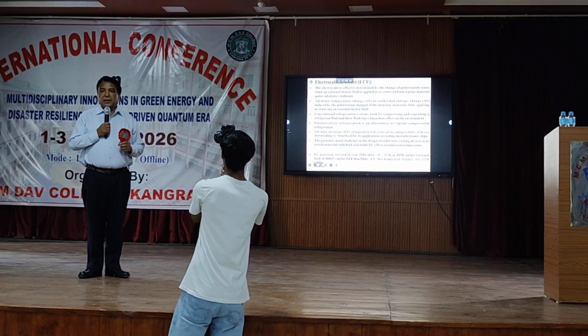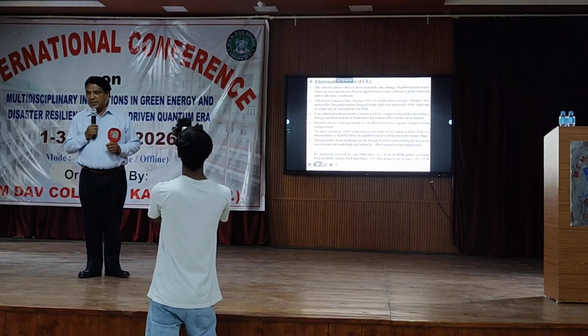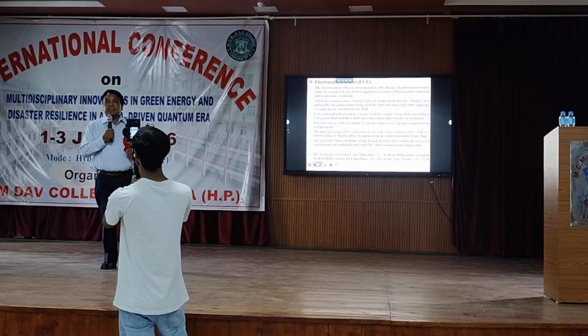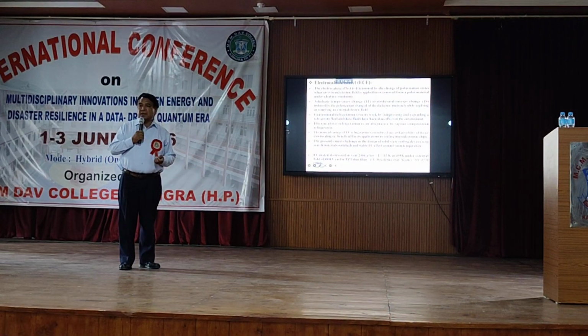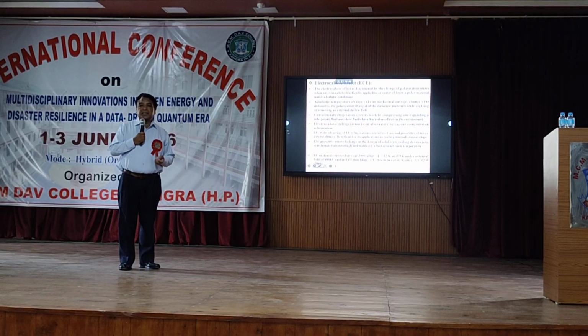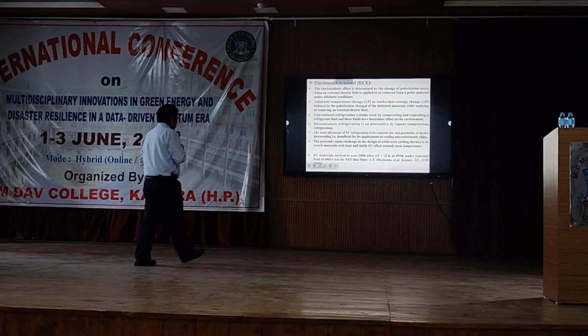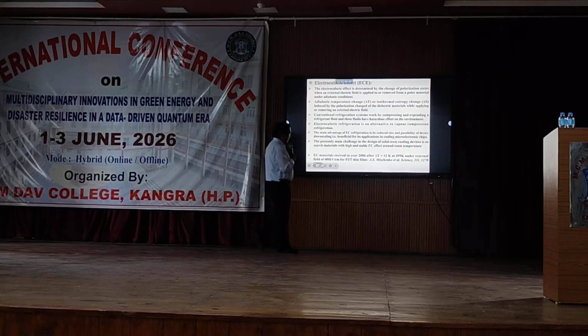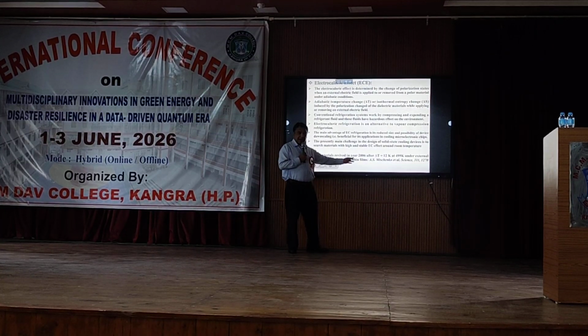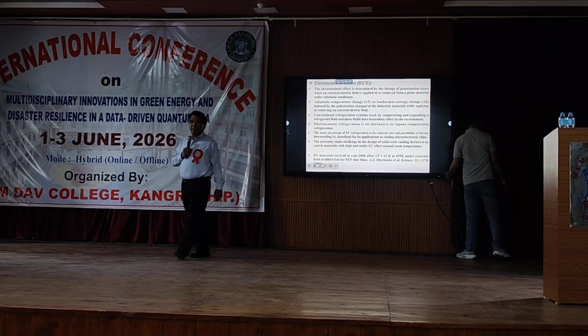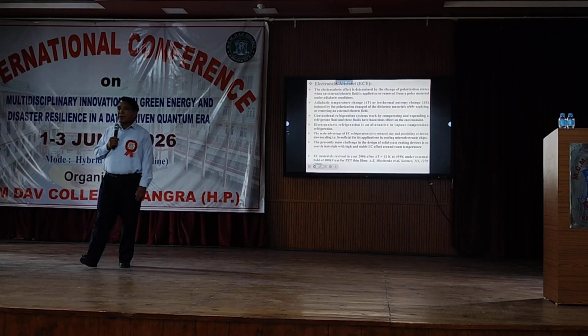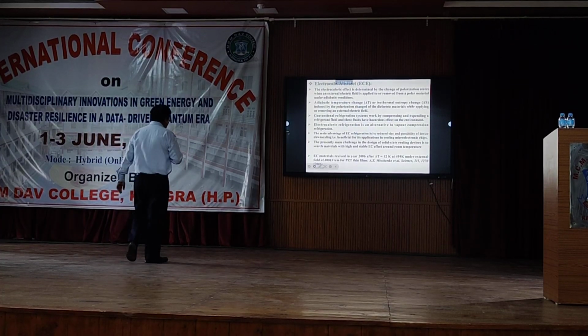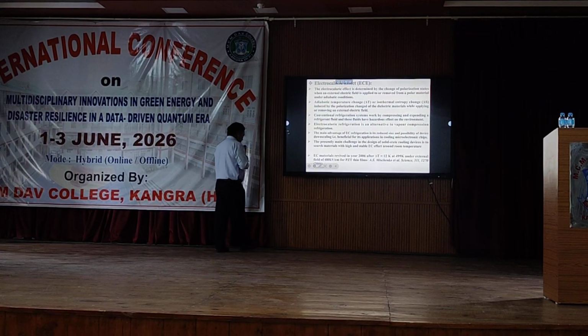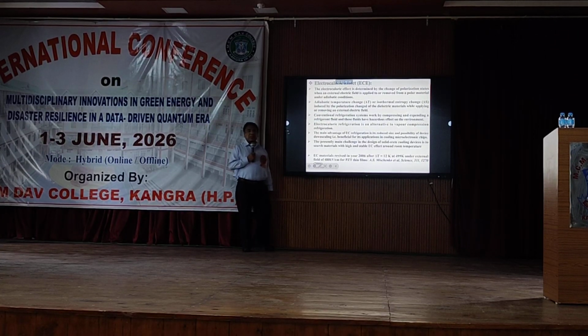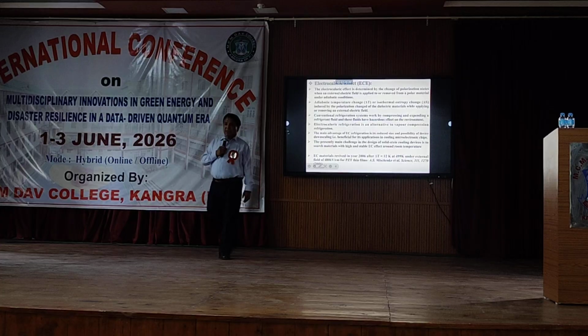advantage of electrocaloric effect based material is, one is environmental friendly, and second is we can miniaturize the refrigeration system so that computer chip or high-end chip can be cooled effectively. Here is one example, the very high delta T, adiabatic temperature change, observed in 2006 for lead zirconate titanate film, but this material is lead based, which is environmentally not good, and therefore research is focused on developing lead free system with high temperature change on applying the electric field.